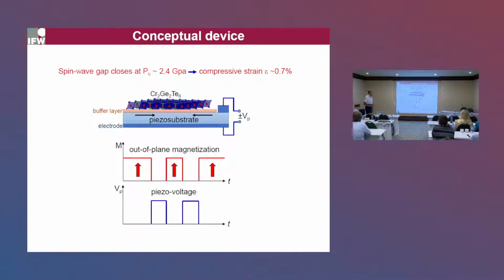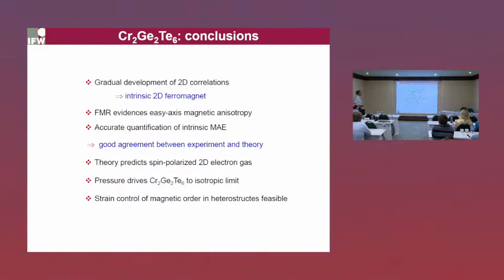We can integrate this kind of bilayer into some spintronic device, for instance, to generate and manipulate spin-dependent currents. So that brings me to the conclusions: we can show that bulk crystals of this material still show the properties of an intrinsic two-dimensional ferromagnet, which has an easy-axis magnetic anisotropy, and we can accurately quantify its value and show that it's out of plane, easy-axis anisotropy, in good agreement between experiment and theory, which also predicts that if doped, we could have an almost fully spin-polarized two-dimensional electron gas.